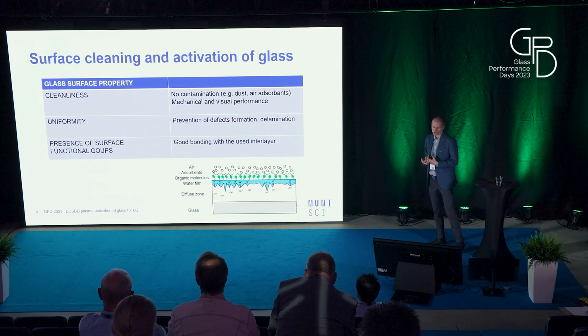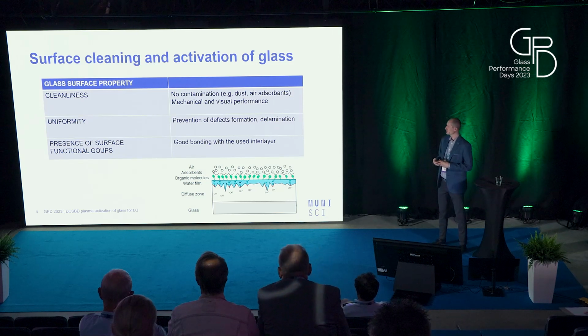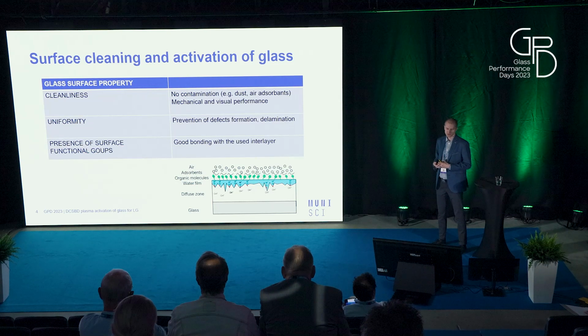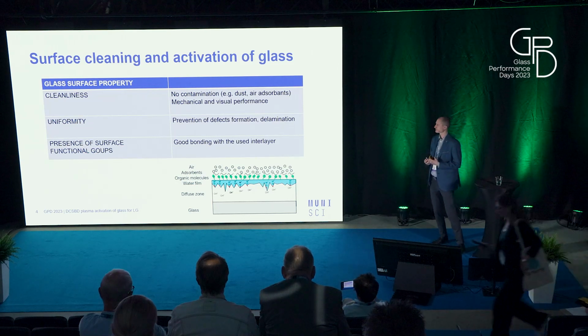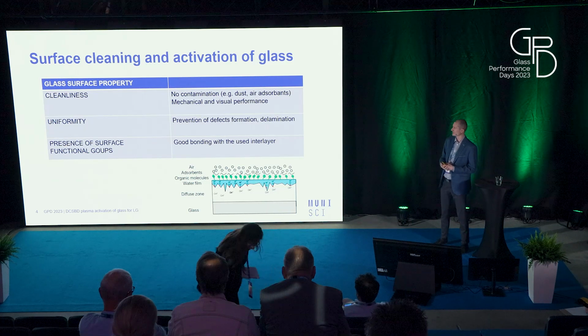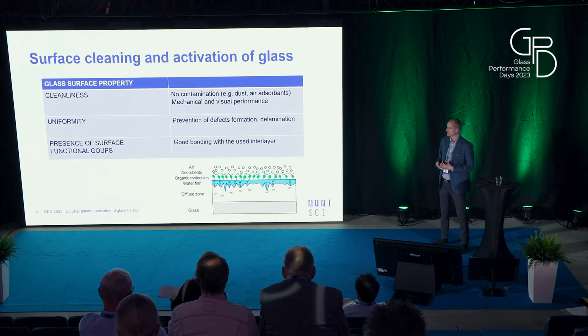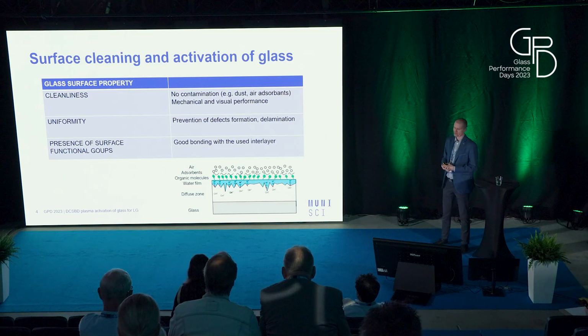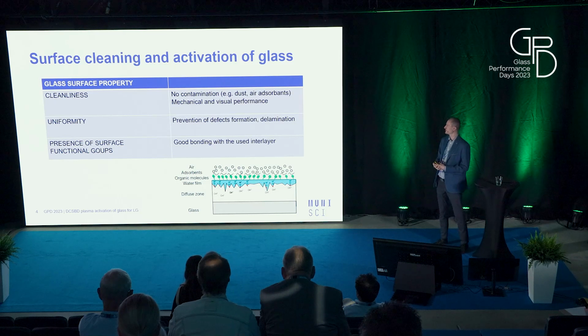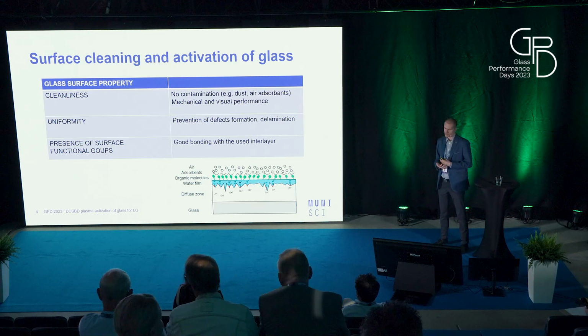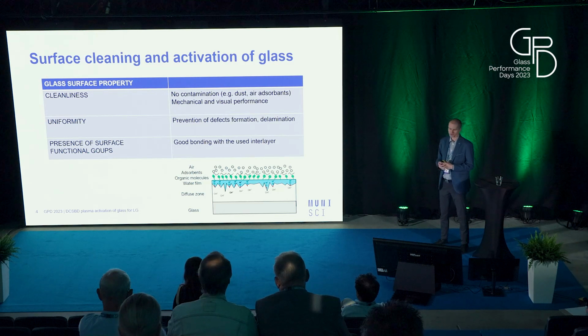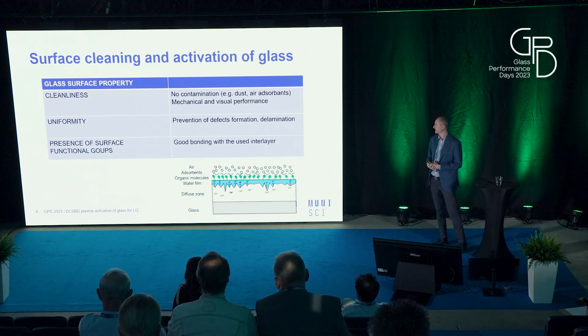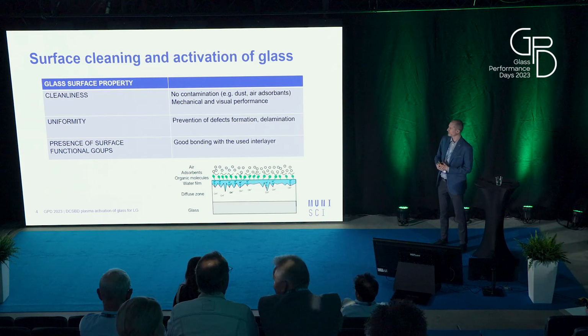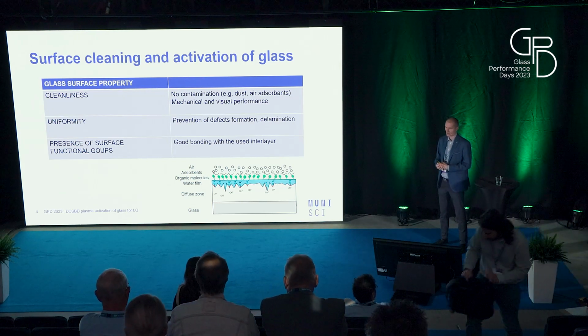For glass, it's important to have a clean glass, to have good uniformity, and also to create some functional groups on the surface. Why do we need this? Because it's important for the mechanical and visual performance of the laminated glass. For example, uniformity is especially important to prevent the formation of defects or delamination on the edges of laminated glass. And of course, functional groups are very important if we need very good bonding between the glass and the interlayer.